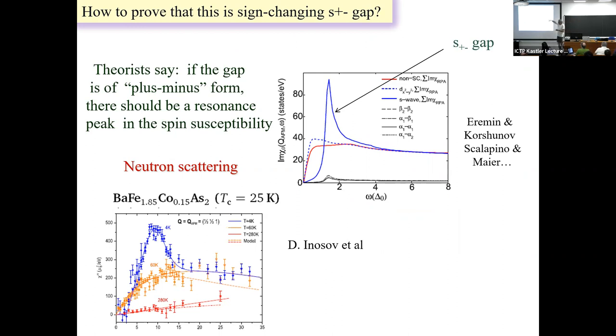And the same happens here. I mean, if the gap changes sign at some momentum, and you ask what superconductivity does to the spin response at this momentum, because of the sign change there is a game of coherence factors, and you get a resonance peak below 2 delta. This is what theory says. Doug Scalapino and Tom Maier did calculations. Ilya Eremin with Korshunov did calculations. And this experiment from the IFW group in Germany. And you clearly see that this is the momentum connecting the centers of hole and electron pockets. Exactly the right momentum. You judge for yourself, but to me, there's clearly a sharp peak that emerges below the superconducting temperature, as you expect for a sign-changing gap. There is evidence from STM, but let's not talk about this.